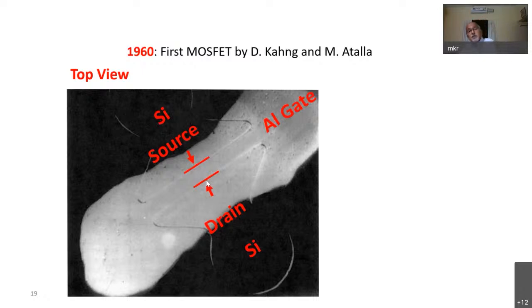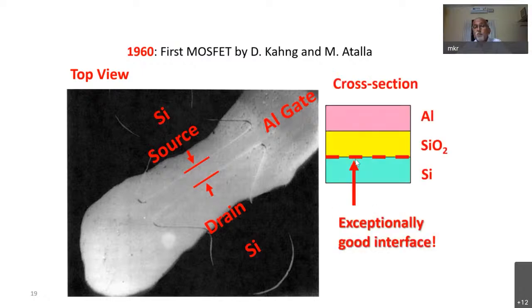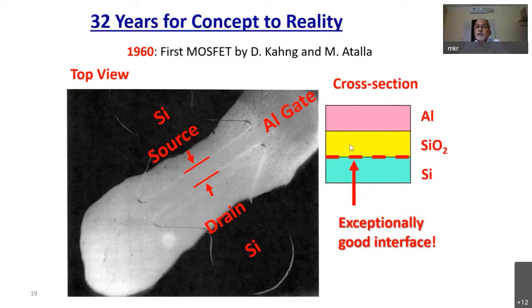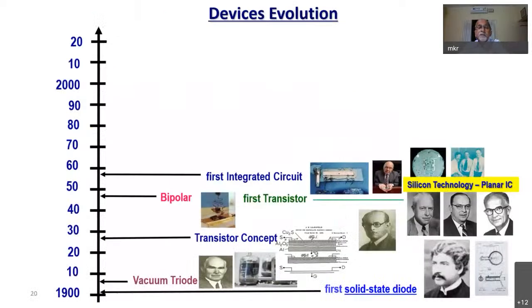You remember that the concept of the MOSFET was in 1928, but the actual MOSFET could be manufactured only in 1960. The problem was the exceptionally good interface. If this is the cross section: silicon, insulator silicon dioxide, and the metal aluminum. So we need an exceptionally good interface between the silicon and the silicon oxide. With the 20 micron technology, probably a few nanometer defect at this site may not be a problem, but still they could not make it for 32 years. That is why in 1960 they could make the device. So this is the 32 years of delay.